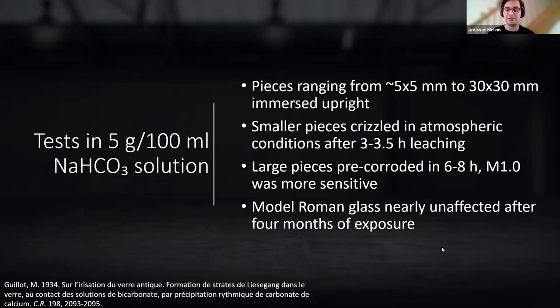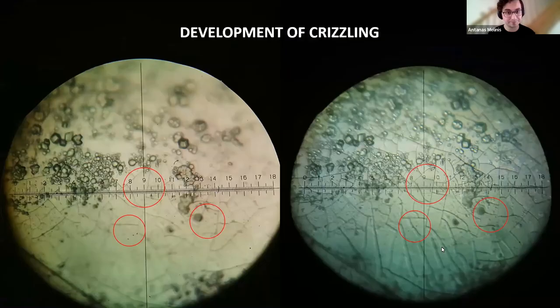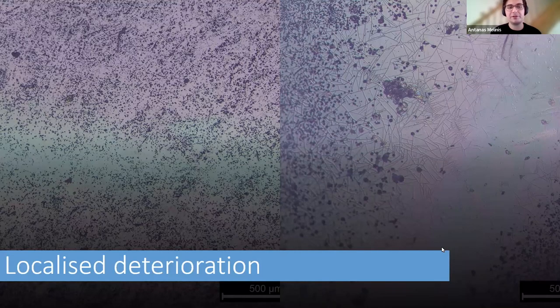Again, the Roman glasses were just as resilient as they were in acid, except for some of that thick iridescent patina that Gio also described. In this quick picture, you can see the development of crizzling in sort of real time. You can see the cracks appearing in the M1.0 glass after 8 hours. The finer crizzling on glasses usually signifies more advanced crizzling. Localized deterioration: within the same piece, you can have different patterns of extraction of minerals, these black dots everywhere, which also result in different patterns of crizzling. And you can see fewer cracks where there are fewer alkaline components extracted.